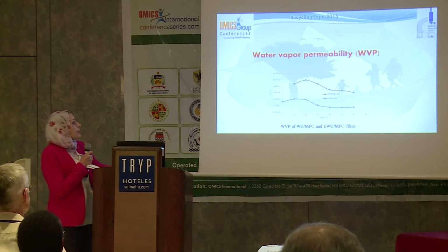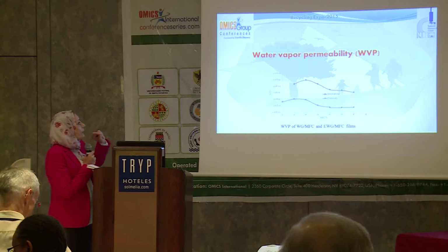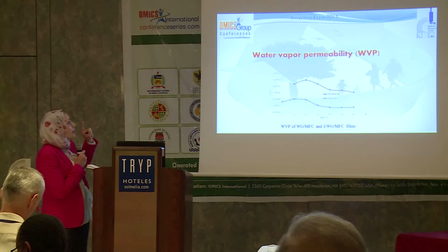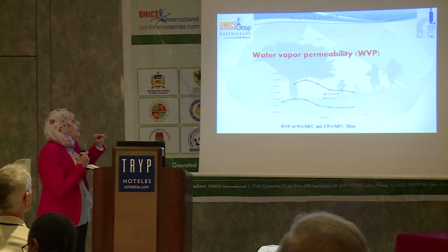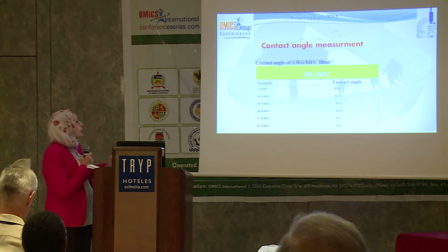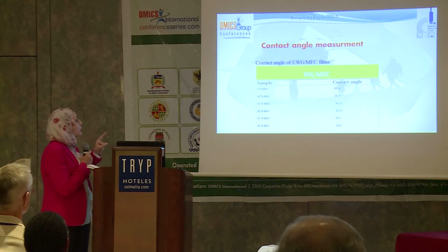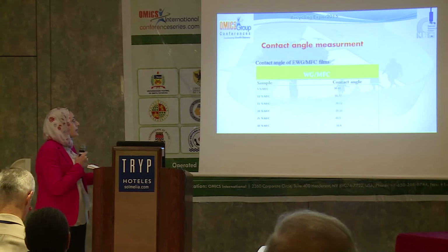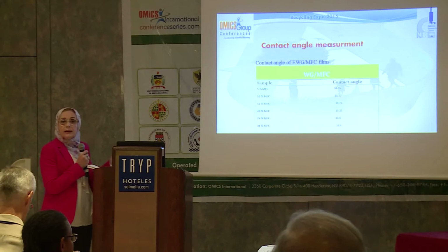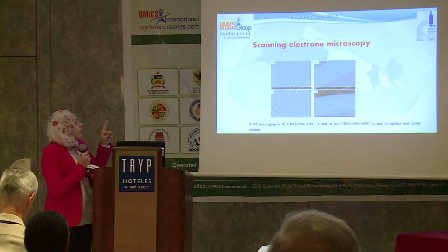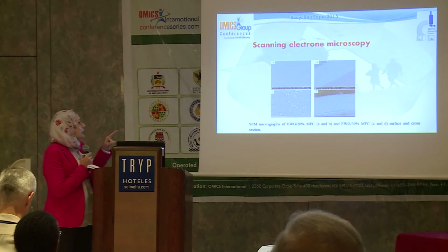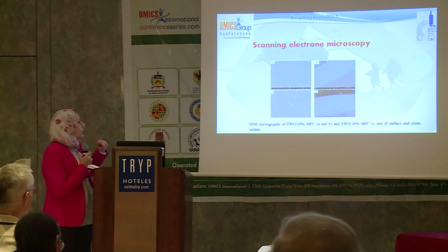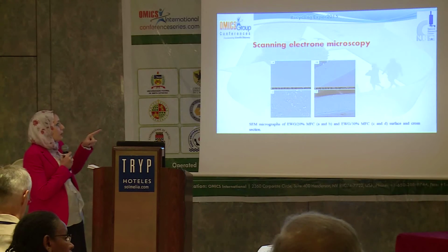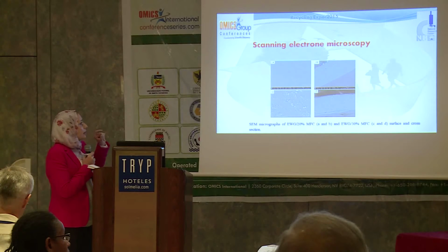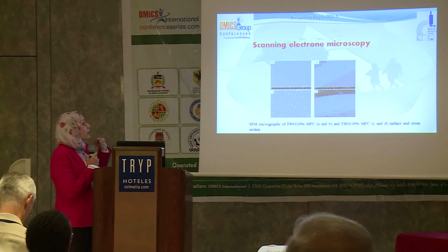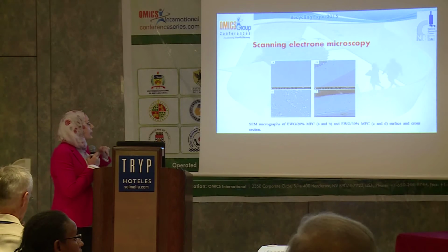Also, in the comparison between the water vapor permeability of enzymatically denatured and chemically denatured wheat gluten, the chemically denatured showed less permeability, which is better than the enzymatic denaturation. Contact angle measurements also did not show a hydrophobic nature like the chemical denaturation. Here is the scanning electron microscopy of the enzymatically denatured wheat gluten filled with microfibrillated cellulose. The films were homogeneous for the low percentage of microfibrillated cellulose, and 30% of microfibrillated cellulose resulted in aggregation